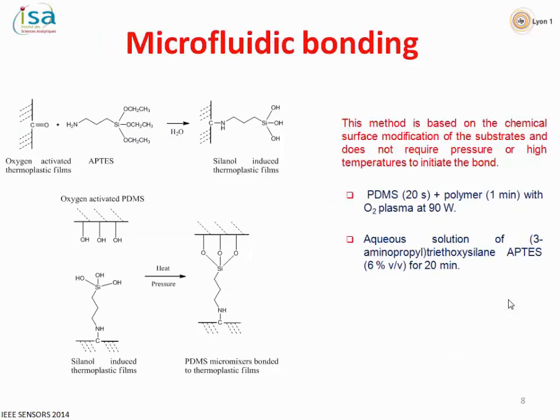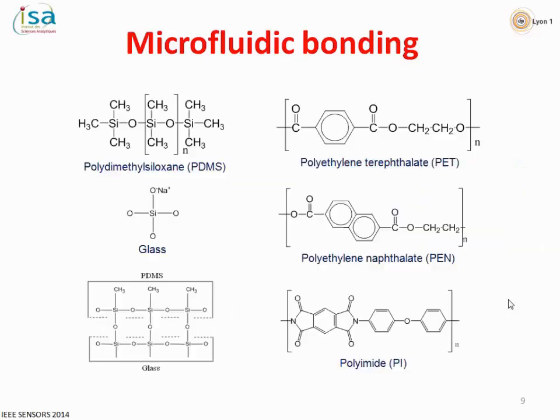Well, now we have the microfluidic structures, and we need to close the channels because we need to inject. For that, we start using silane groups, and we do activation with plasma, and we do the functionalization with the silane. And this part, basically, we use PET, PEN and polyimide, and after that, we do oxygen plasma in order to activate PDMS, and after that, by simple contact, we have a good bonding.